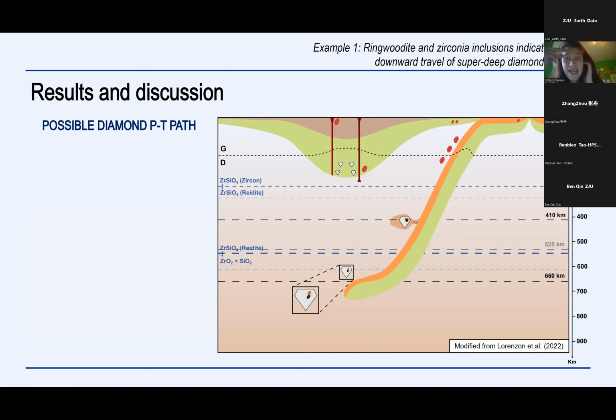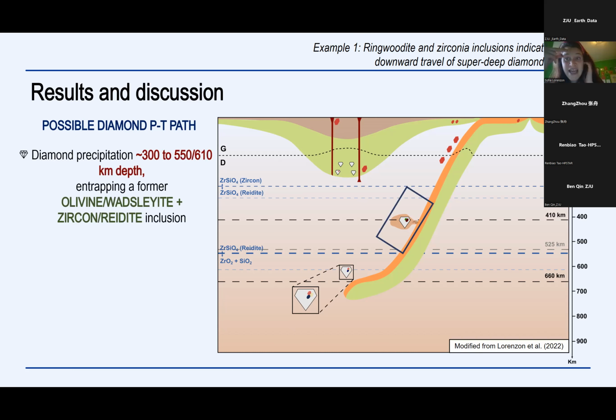And considering the fact that our diamond is a super deep diamond, we suppose that probably our diamond precipitated in a depth range between about 300 kilometers, which is the minimum depth of formation for super deep diamonds, sorry, and a depth of about 550 or 610 kilometers, which is the depth at which reidite will transform into stishovite plus orthorhombic zirconia. And during its precipitation, this diamond entrapped a former inclusion composed of olivine or wadsleyite plus